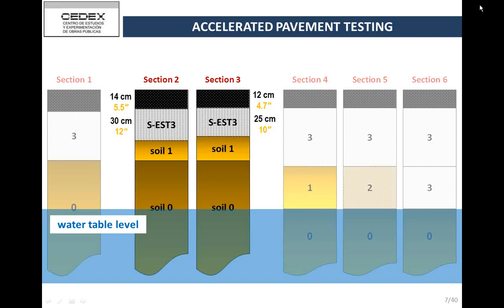But at the very surface, you have this layer of very crumbled material, where you lose the bond with the asphalt layer. In your case, I think because you have such thick asphalt layers, close to 5 inches, you have not seen the slippage cracking that Fred has mentioned. But we saw the slippage cracking in exactly the same way, because our asphalt layers were thinner, and the loss of bond underneath makes the asphalt slide like a carpet. Okay, but that's probably the reason, because we actually didn't see movement in this material. Yes, because your layer is thick.